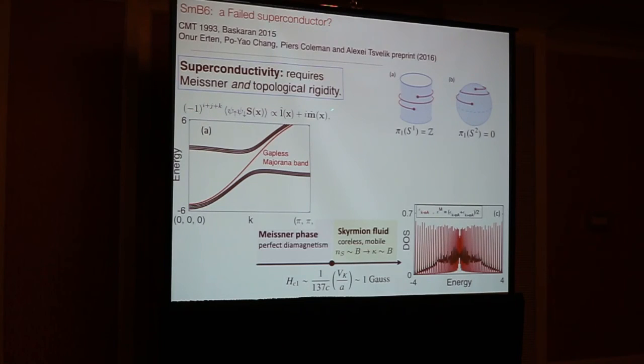So we've tried to look at this order parameter. We've written down a long wavelength action for it. And one of the interesting things is that this order parameter allows for the presence of skyrmions, even though it doesn't allow for the presence of vortices. And skyrmions cost energy to create them. But in a magnetic field, you reach a critical field where actually they start to condense.